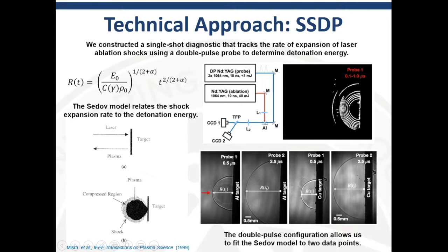It is the Sedov-Taylor blast model that can be applied to laser-induced plasma to describe the evolution of the induced shock, both spatially and temporally. As seen in the equation here, it relates the time and energy to the expansion radius. The laser energy deposited on a target can estimate the energy attributed to plume formation if this equation is rearranged.